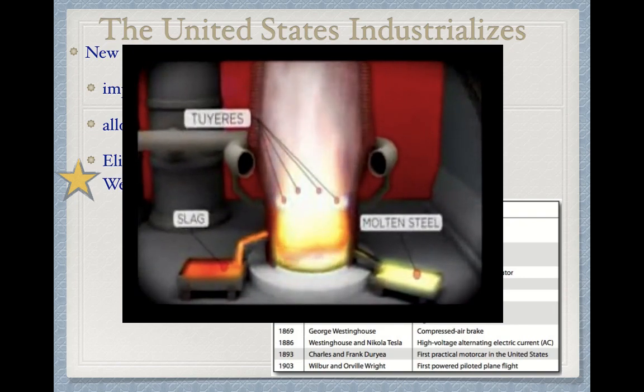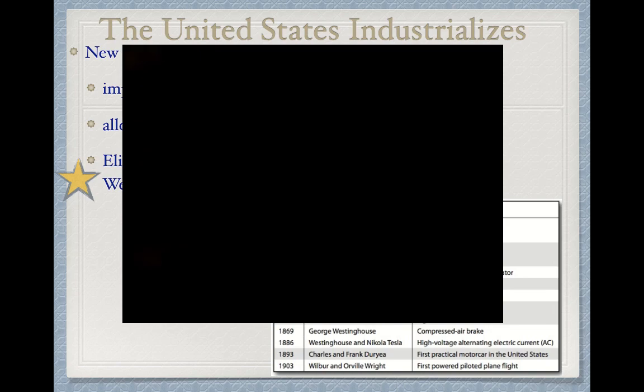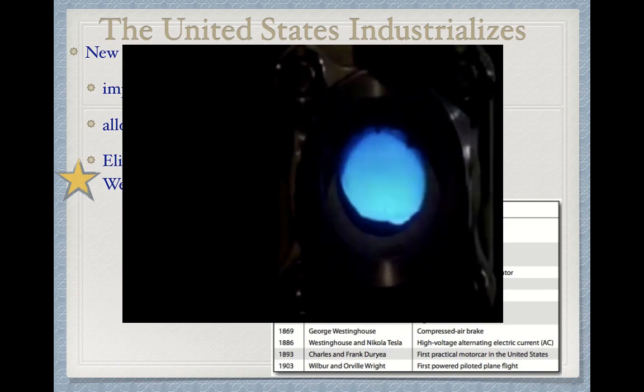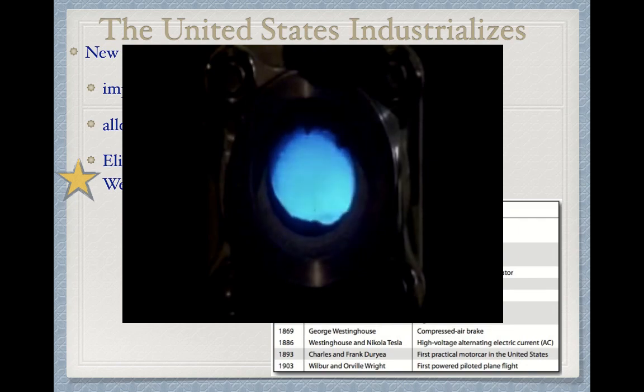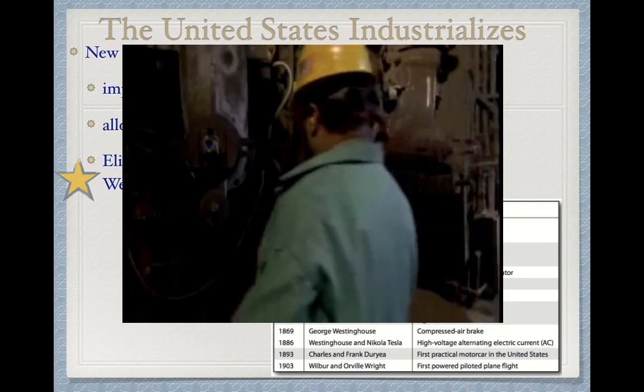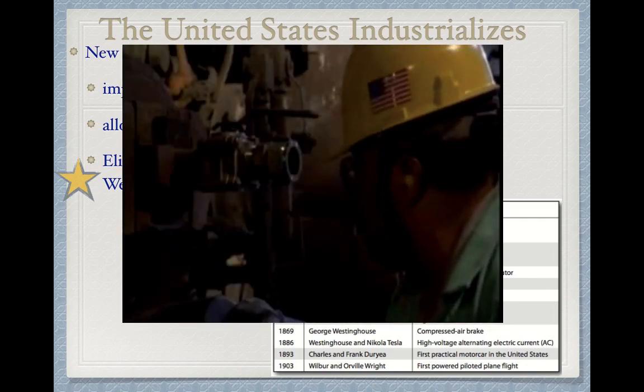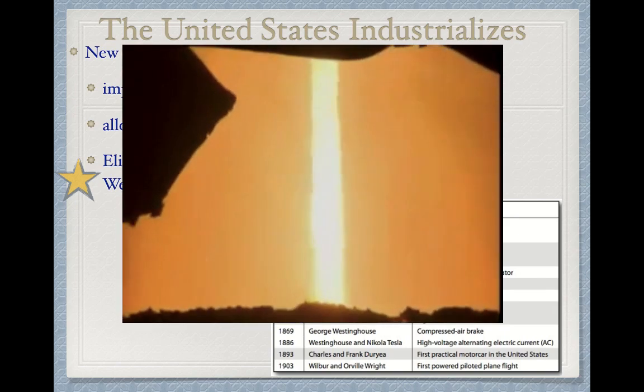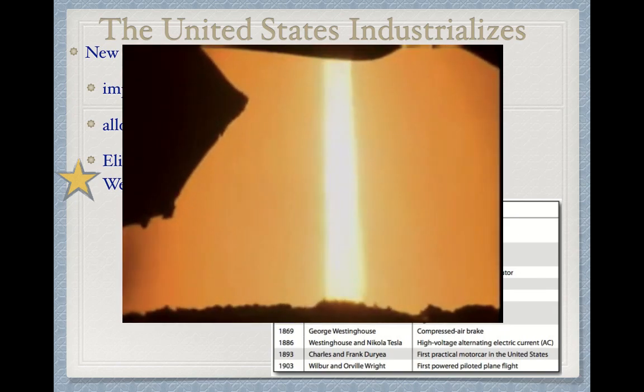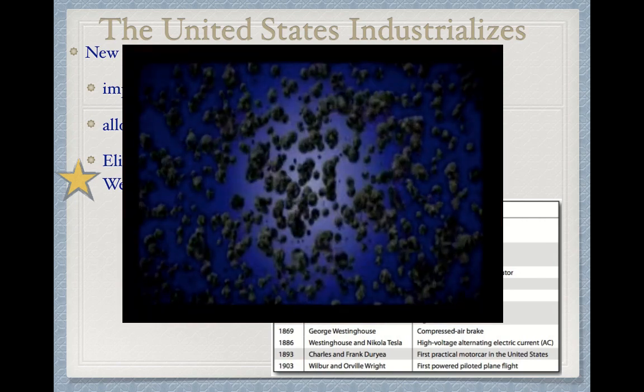That air is pushing up through a solid burden material. The superheated air ignites the coke like charcoal in a grill and heats up the furnace to nearly 4,000 degrees Fahrenheit. At this temperature, the oxygen is finally blasted away, leaving pure molten iron. But it's also doing something even more amazing.